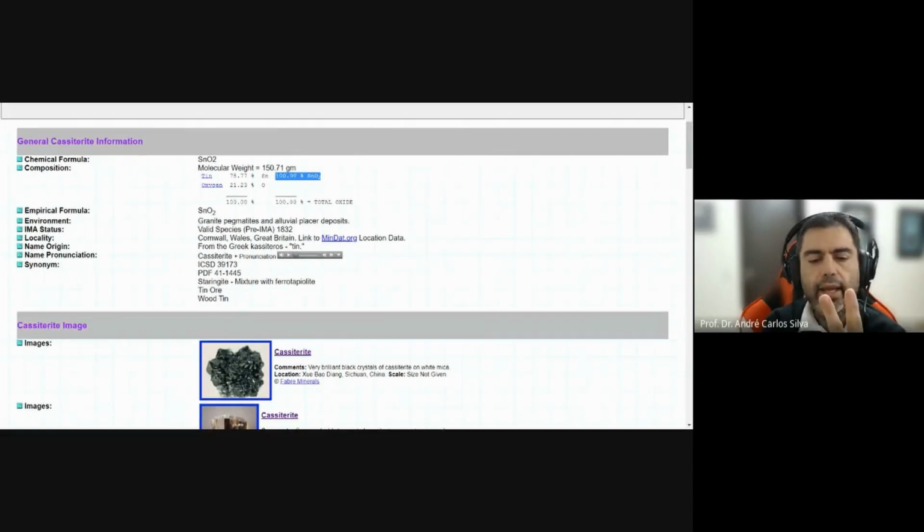And another thing, if I send a sulfide, not an oxide mineral, to XRF, it's going to give me oxide as a result. So that's why it's important for me to have the oxide composition and also the element composition. Keep that in mind. I'm going to show you a more complex mineral later, and then you're going to see why this is quite important. We're going to browse apatite in a few seconds.